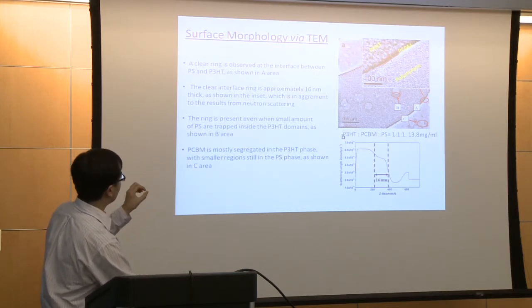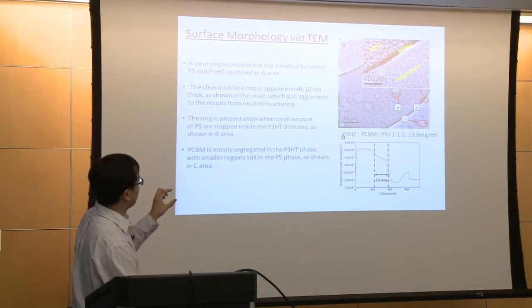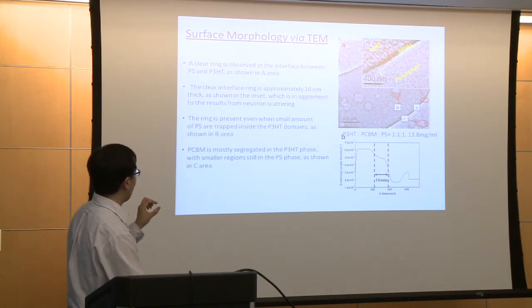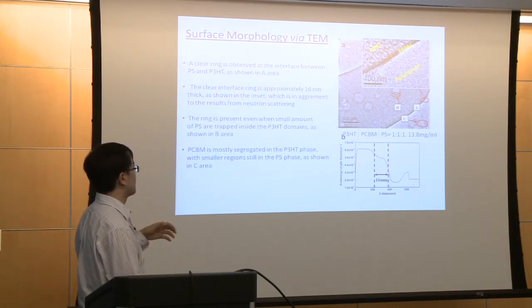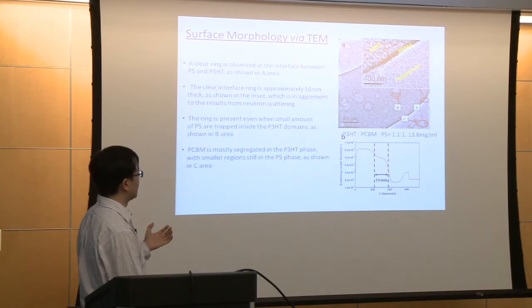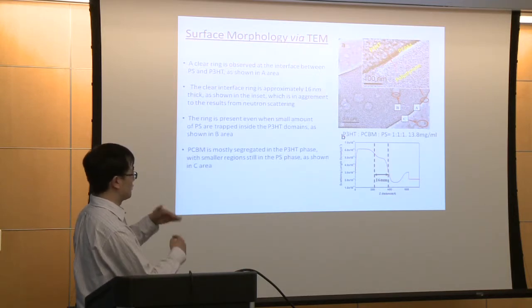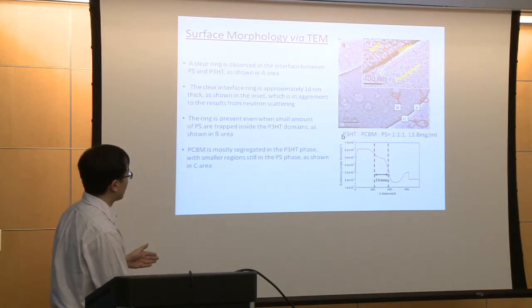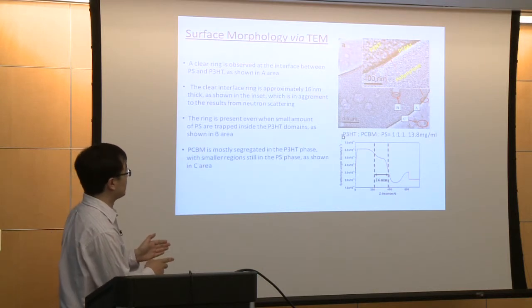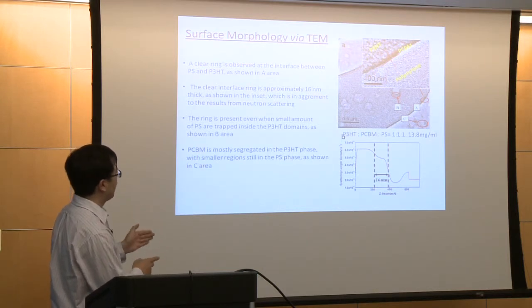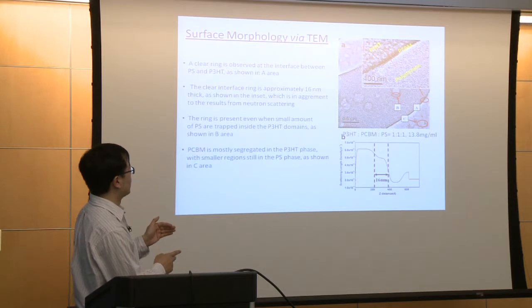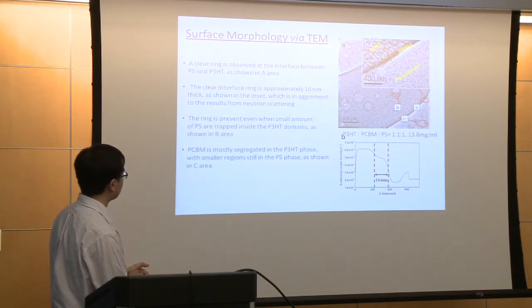Like the A area. And if we enlarge the boundary and measure the width of the boundary, it's about 16 nanometers. And this width is in agreement with the results we get from the neutron scattering. That's the interfacial width between the two layers. So in this way, we can somehow confirm this dark line is actually PCBM, and the other two phases, one is P3HT and the other one is polystyrene.